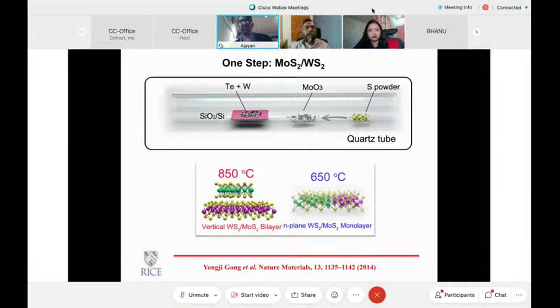And what happens in general, again, this is kind of intuitive in some sense, is that when you introduce two different precursors, let us say you have molybdenum sulfide and tungsten sulfide growing at the same time, you could either have one stacked on top of the other, or you could actually have almost a lateral heterojunction, because at the end of the day, these kind of materials are isostructural. Their lattice parameter is very close. So you could have a head-on epitaxy, and you could just have continuous growth of two different phases stitched together.